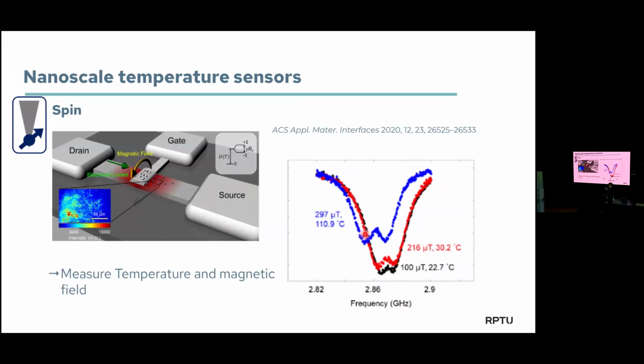Because where you have current in the transistor, of course, it creates a magnetic field. Think of Biot-Savart's law. And at the same time, you can see where the device warms up most. And this is what they have been showing here, that they can show shifts in temperature independent of the shift in the magnetic field. This is an example of measuring temperature with the NVs.